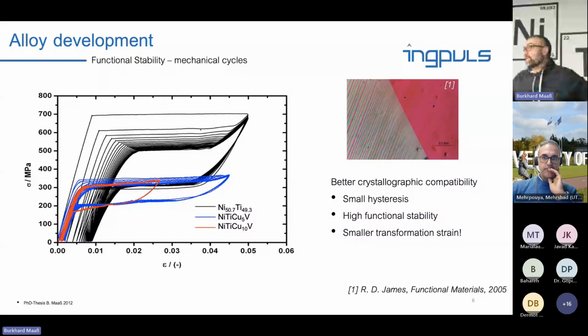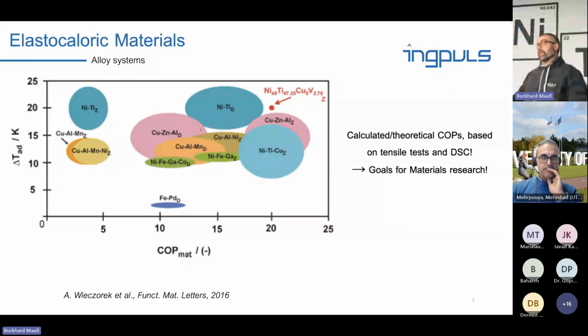Now, this alloy with the 5 atom percent copper, vanadium, let's say, by coincidence, was deemed one of the most promising materials for elastocalorics. When I made this material, that was 2012, I just wanted to have a pseudoelastic specimen. And then my successor, Andre, was sitting in my office after me. He just took this material and did his calculations for elastocalorics, and he found out that this material should have one of the biggest COPs of materials known in the literature. And then he put this to work.